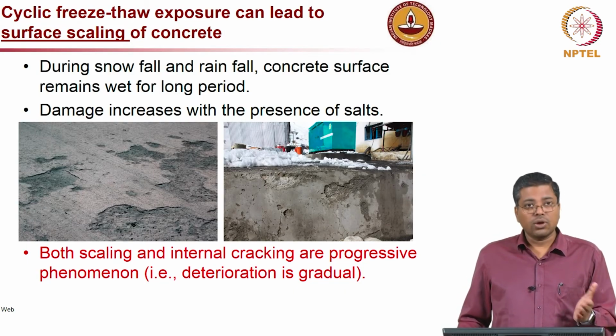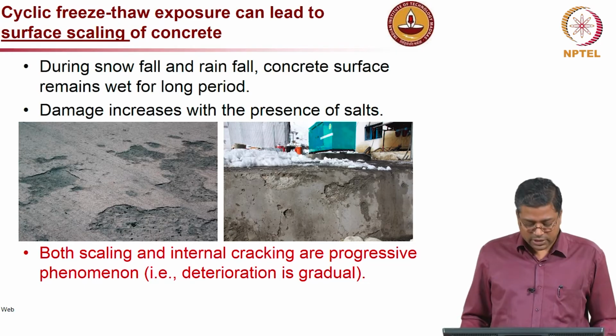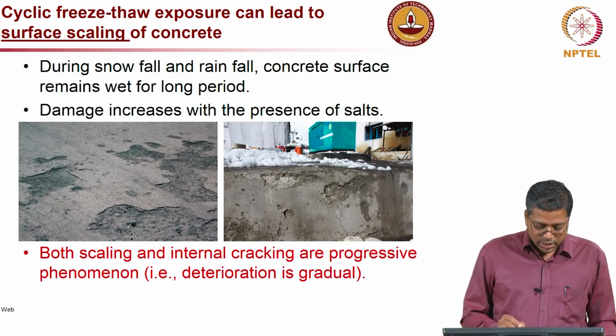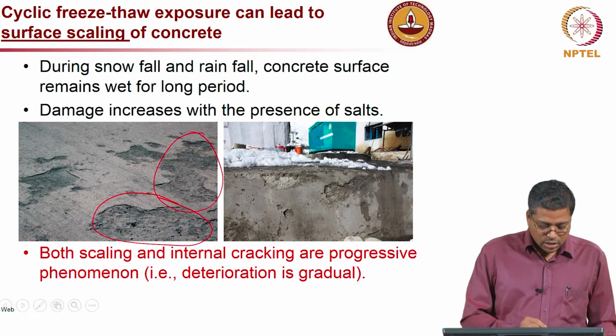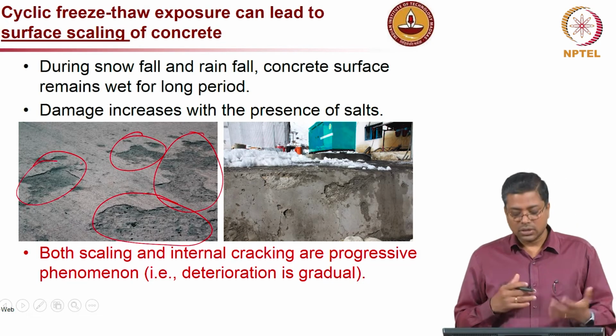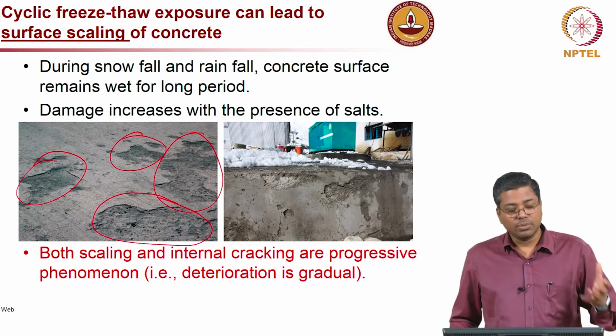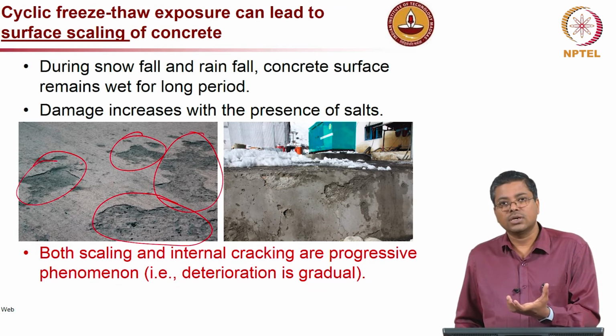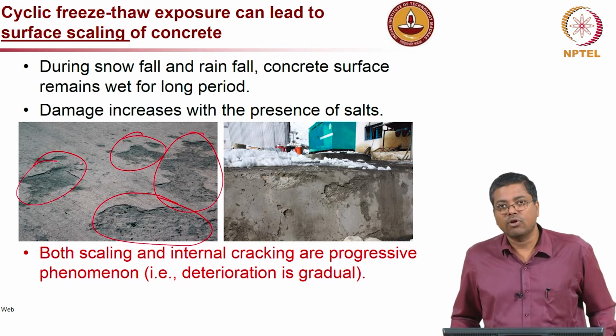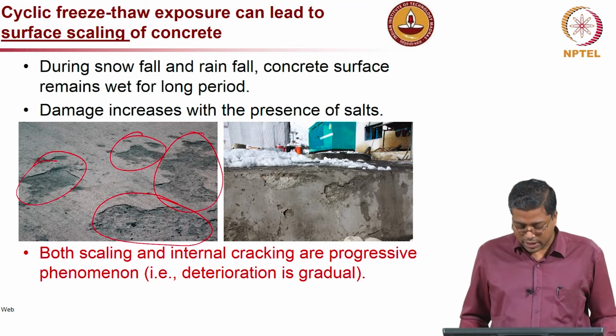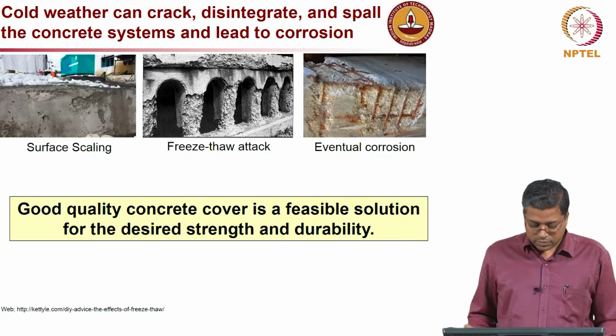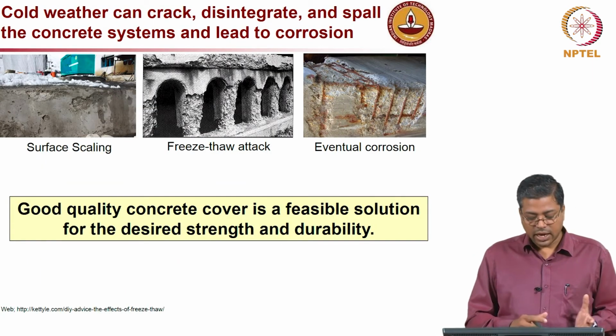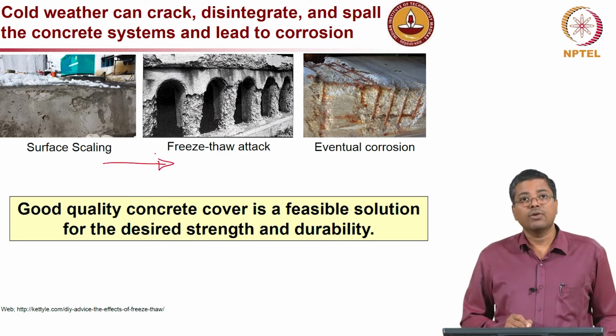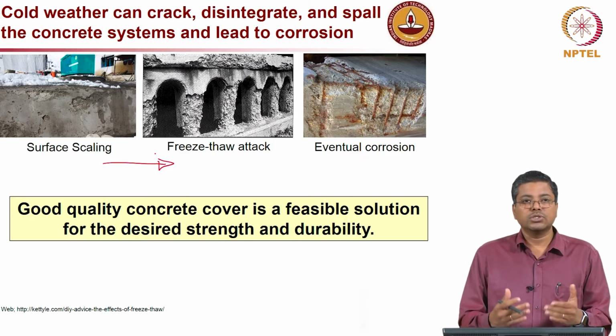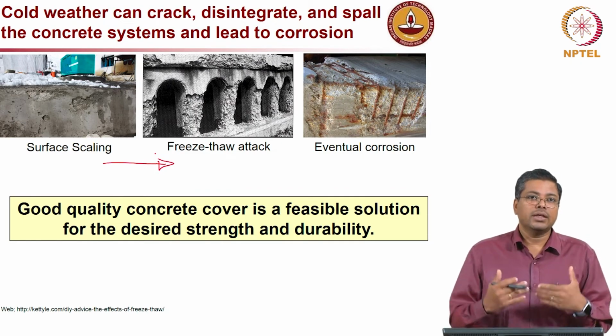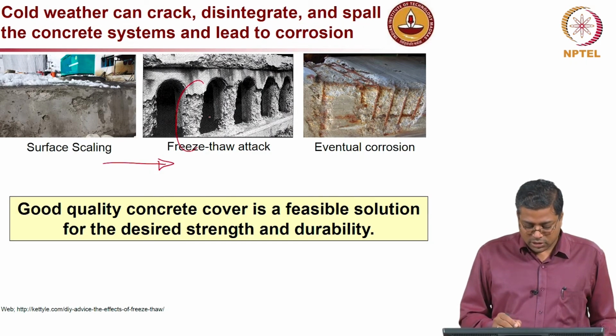Now, this kind of exposure can also lead to surface scaling near the surface. You can see in the picture on the left side, a lot of material is lost at the near surface. This is again because of the absorption of water into the near-surface concrete, and the ice formation leads to cracking of the concrete there. And eventually this surface scaling will happen, and then you will have multiple deterioration, because new surfaces get exposed, and it leads to significant loss of material, as you see in this picture at the center.